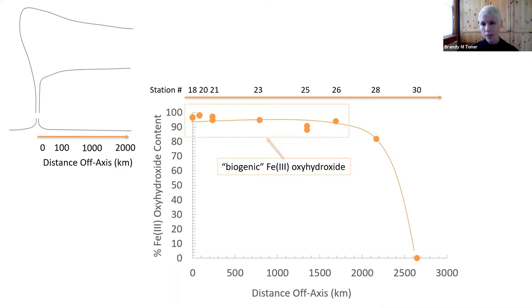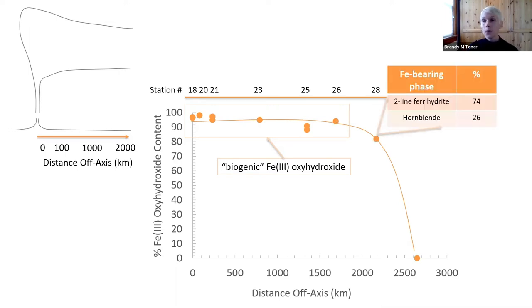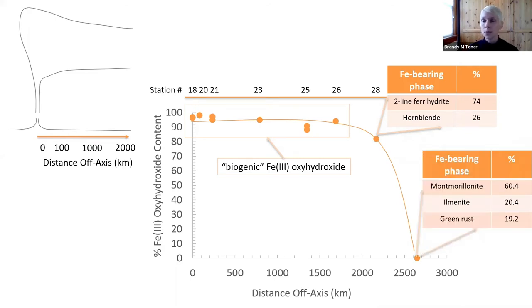As we move away from the axis, say from station 26 to 28, as we move outside of this little zone, we start to see a pretty big change in the particulate iron speciation. There's still a lot of iron 3. It's in the form of a two-line ferrihydrite-like material, but then we also have hornblende, which is a primary silicate, probably a continental source. So it looks like we may have lost the plume at this point, the hydrothermally derived particulate iron. And then as we move out to station 30, it just becomes even clearer that we've got another source of particulate iron contributing to the water column, very likely no longer our original hydrothermal source.